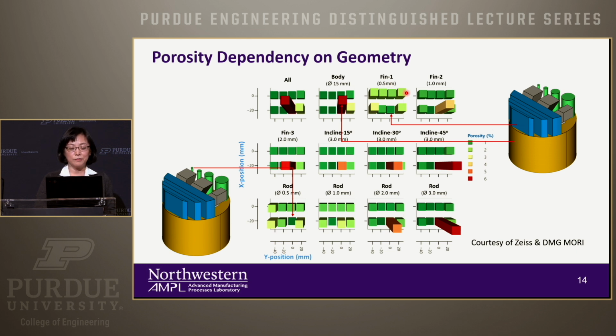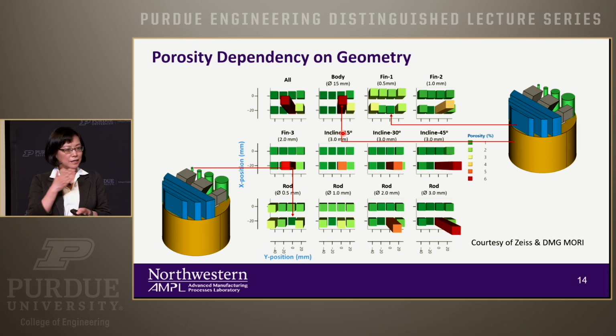If you count the fin 1, fin 2, and so on, for each one you look at the porosity volume. What you can see is that this one, for example, is very nice, the green one for this little thing, but it's very bad for the body, right? So the question is, this illustrates that the same process condition really depends on your geometry and where you are. It will change the results quite dramatically.